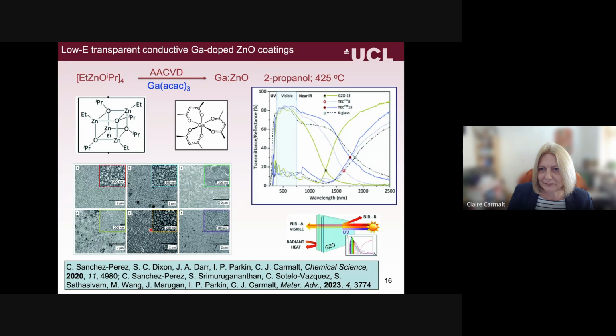The other thing that was really interesting when we looked at the transmittance and reflectance properties is that it actually showed really good properties for low emissivity or low E window coatings. Now these are important coatings because they improve the insulating properties of windows. To get a low E window coating, you have to have high reflectance in the mid or far infrared, and you have to have high transmittance in the visible.